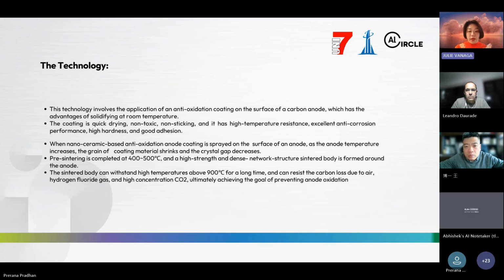Unlike traditional coatings that require high temperature curing or have poor adhesion, our coating has the outstanding advantage of room temperature solidification, which means it can be applied directly in smelter workshops without additional curing equipment. Usually, after you spray it and let it dry for 4 hours at normal temperature, you can put it directly into the pot. But if you spray it in extremely cold temperatures, such as Norway at minus 15 degrees, maybe wait 12 hours for it to dry, and then you can put it into the pot directly.